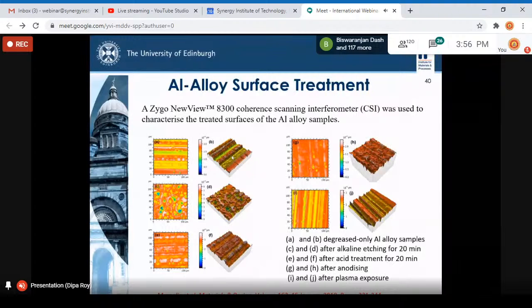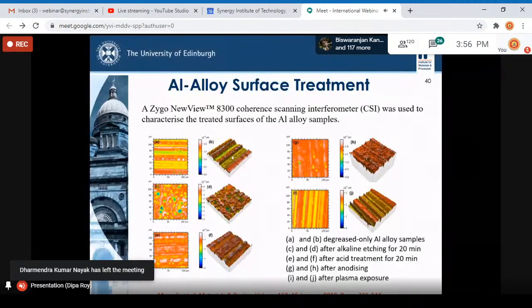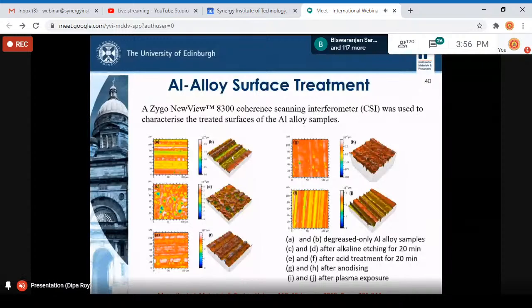Now, in the case of such hybrid materials, the most important consideration is the interface, because we are trying to bond the composite with the metal. And in the case of liquid acrylic resin, we are manufacturing and bonding in situ during the composite fabrication. So it is very important that the surface of the metal is prepared well enough so that it can have the right bonding with the composite, because they are very dissimilar materials, chemically very different. So they don't have any affinity to bond with each other. That's why we have to have the right surface treatment of the metal alloy to make it ready for bonding with the manufacturing. Now, we tried different chemical and physical treatments.